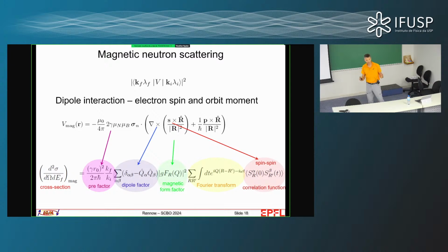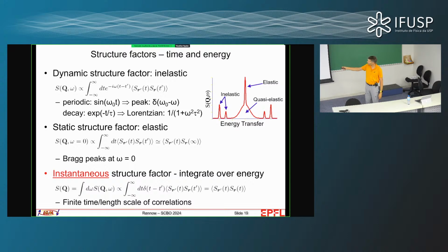It has a magnetic form factor, which tells me something about the size of the electron cloud that carries the magnetic moment. And then I have the Fourier transform with respect to space and time of something as simple as a spin-spin correlation function. So basically the correlation function between a spin on one site at one time with a spin at another site at a later time t. Okay? And this quantity, the spin-spin correlation function and the Fourier transform thereof, which we like to call the dynamic structure factor, has encoded into it a lot of the properties of a collective system, because it tells us what is the correlation between different sites at different times. And for instance, if I have something oscillating inside this system, you are familiar with phonons, right?